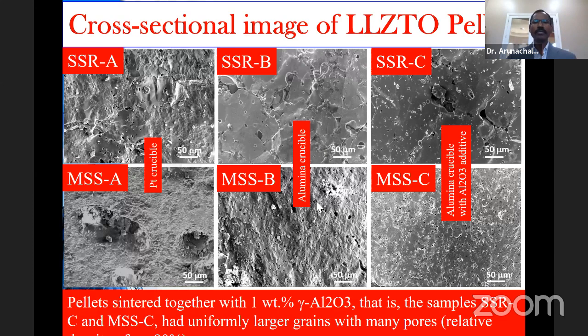The ones for the alumina crucible, on the right-hand side, you can see there are more pores for both the pellets. In fact, the pellets sintered in alumina crucible with aluminum oxide as sintering aid, for the powder made by solid-state reaction, can have some cracks and also a larger opening inside the pellets. So there are relatively more pores in the grains, mainly because of the aluminum oxide as a sintering aid.